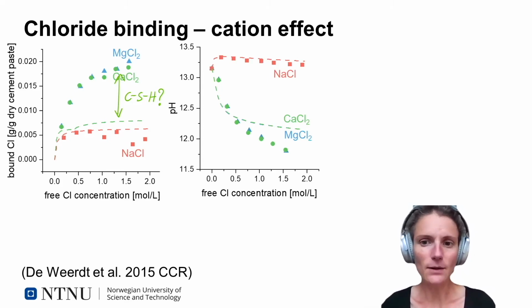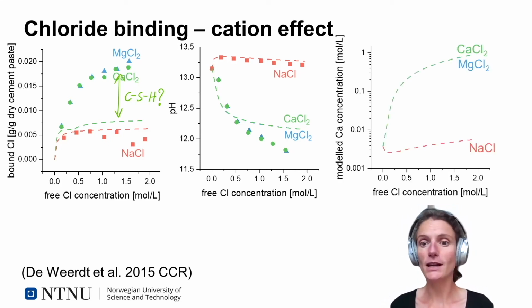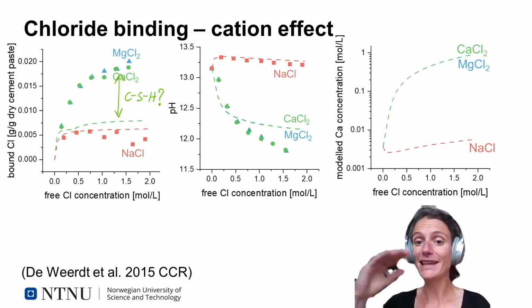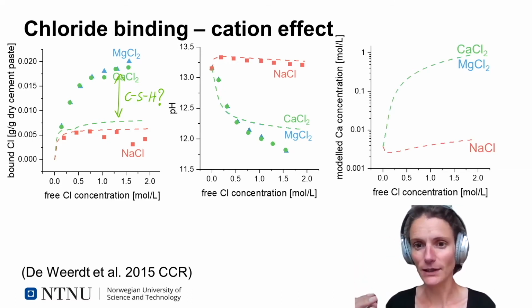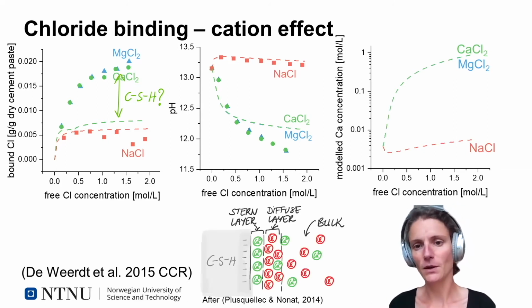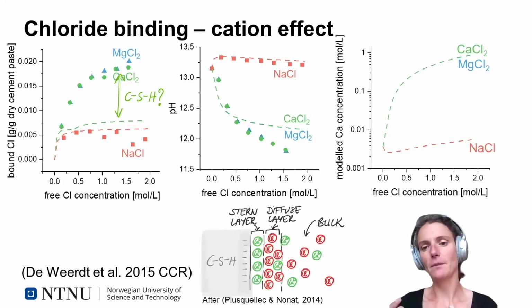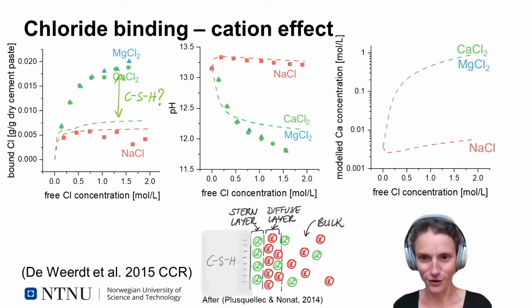So this decrease in pH in the case of magnesium and calcium chloride is associated, according to the model, with an increase in calcium concentration. And it's this increase in calcium concentration which actually can increase the capacity of the CSH to attract chlorides.